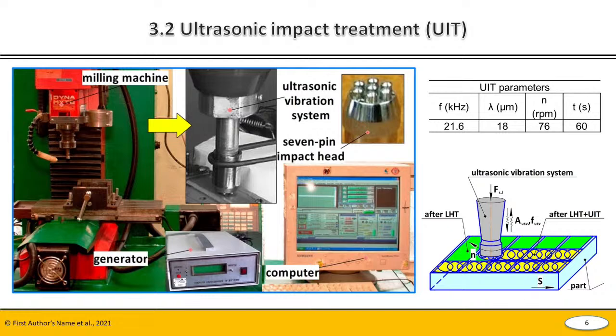The ultrasonic impact treatment of the specimens was conducted using a special multi-pin impact head with 7 pins. The ultrasonic vibration system was mounted on a milling machine with numerical control and pressed to the specimens with 30 Newton. The scheme of the ultrasonic treatment you can see on this slide. Also, the optimized ultrasonic parameters are presented in the table. Next slide, please.